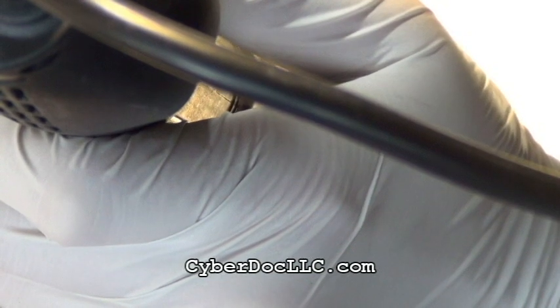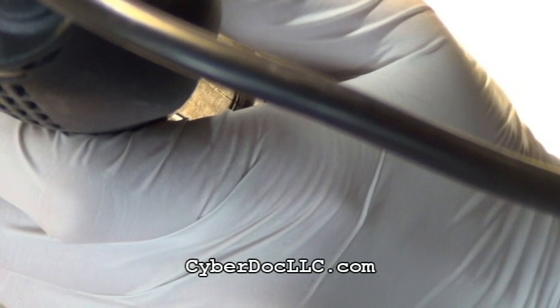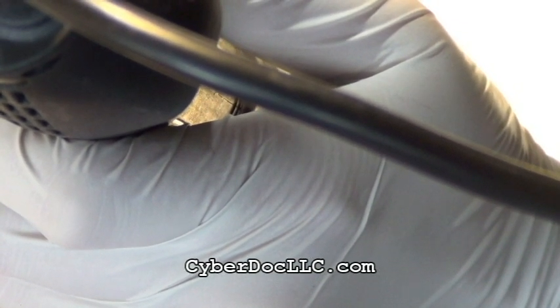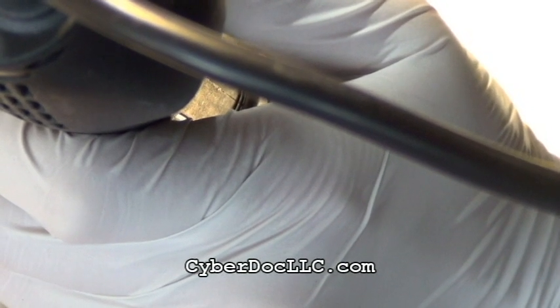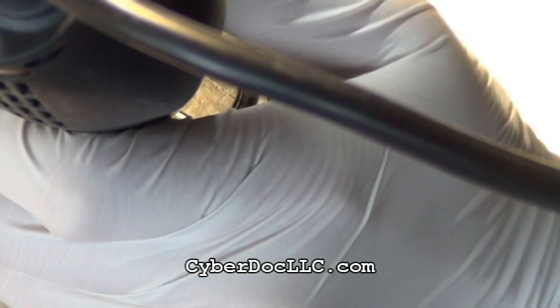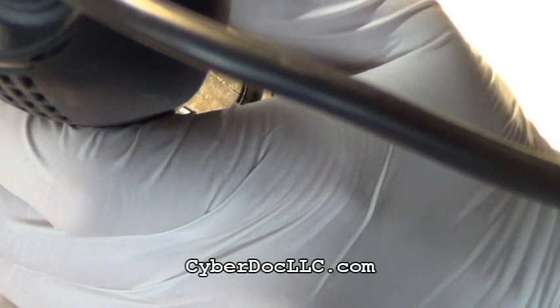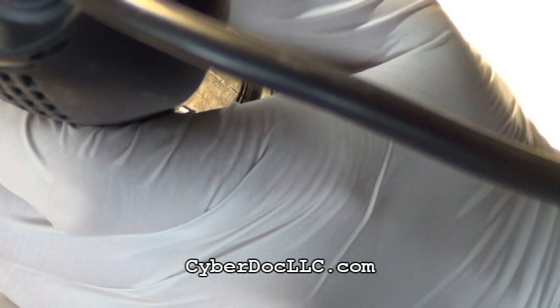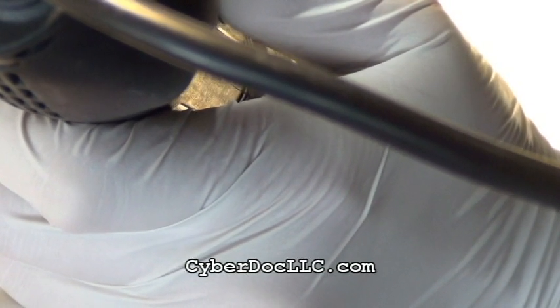Your heat gun and this heat gun are not going to have the same profile. The important thing is you don't want to go over 300 degrees Celsius, because that will start burning off the parts on the board. The logic board from Apple is designed to withstand up to 300 degrees Celsius. So it's not going to be damaged at 300, but if you go up to 400 degrees or 350, there's a chance you might start burning off stuff.